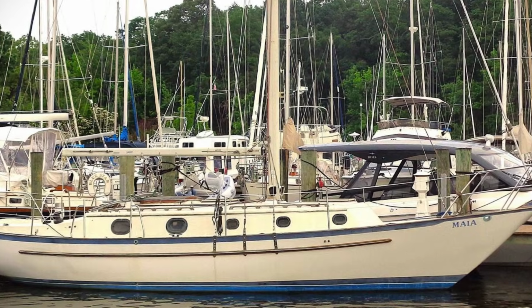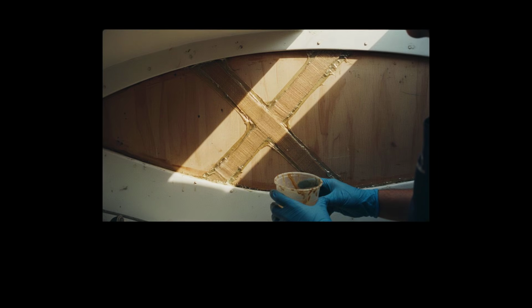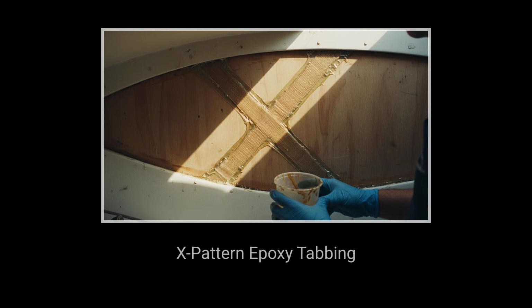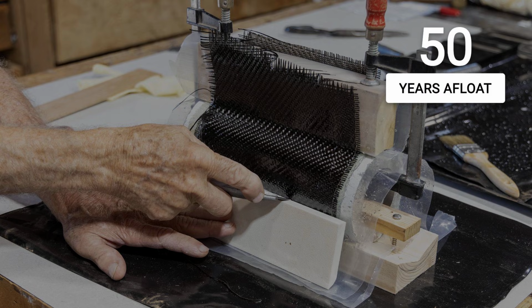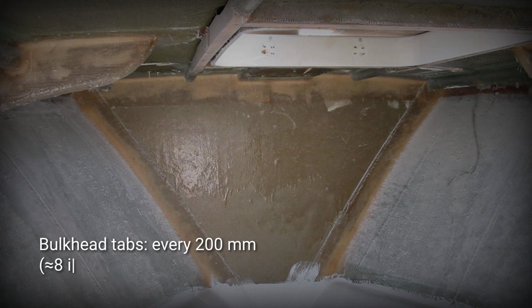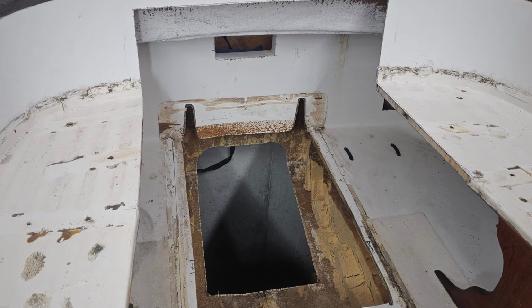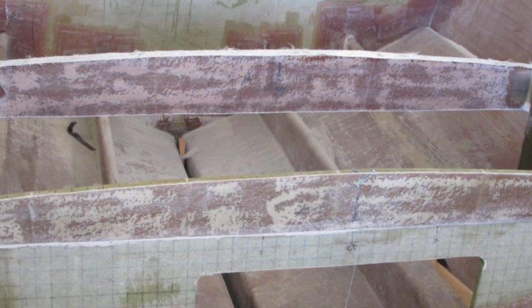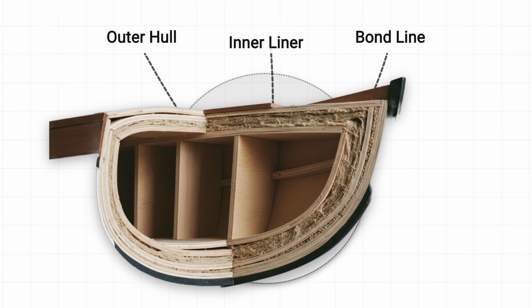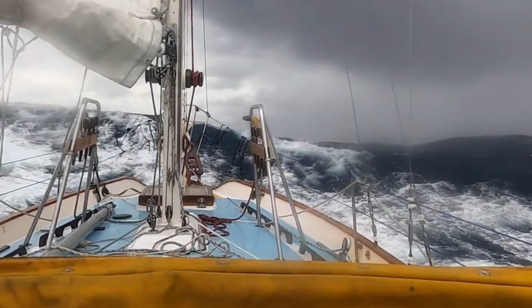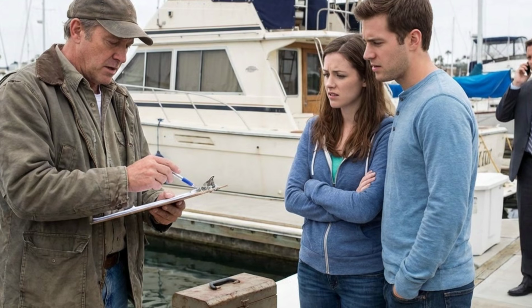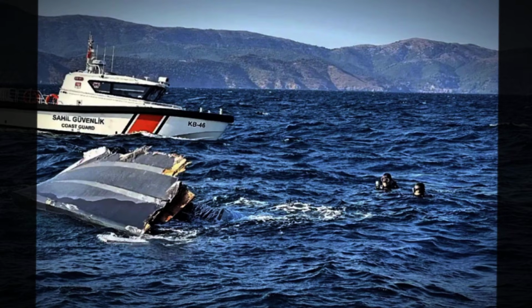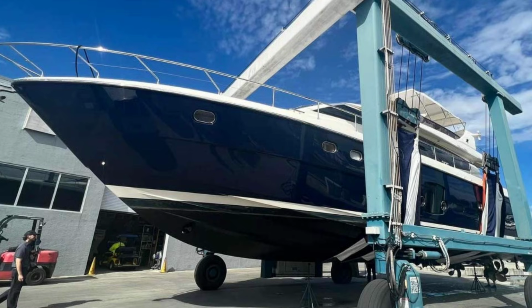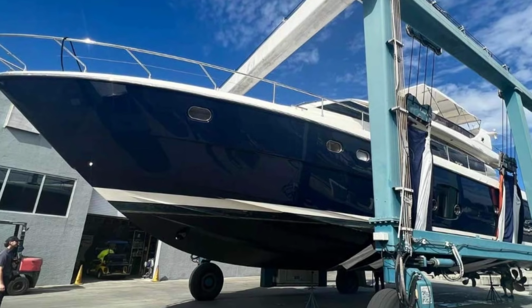Pacific Seacraft took this logic even further. Their 37-footers use an X pattern of glass epoxy tabs, each 30 millimeters wide and 6 millimeters thick, spaced every 200 millimeters, about 8 inches. Every bulkhead is a solid glass block, tab bonded on all four sides, corners laced with that X pattern for redundancy. The result is a continuous sandwich, inner liner to outer hull, that resists torsion and flex. Failures are almost unheard of. When they do happen, it's usually from a collision, not from the slow, invisible rot of a failed adhesive bond.